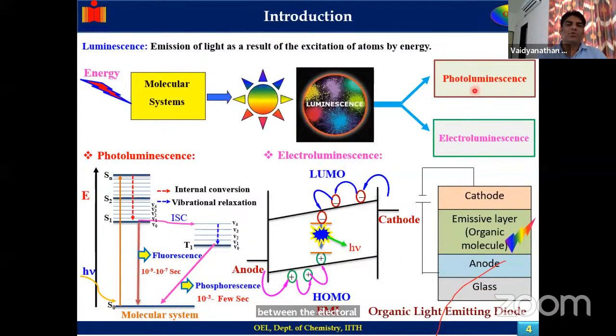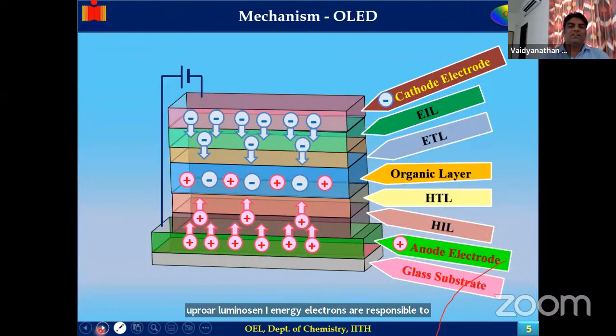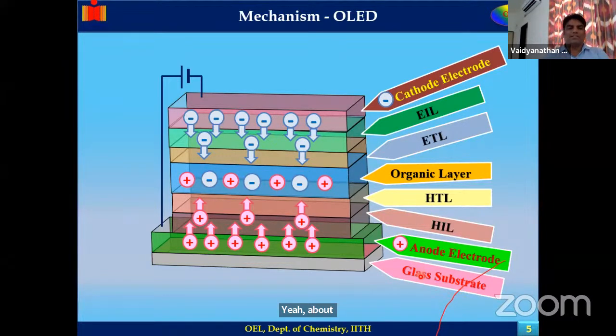Here in photoluminescence, the photon is the responsible source to get a luminescence, whereas in electroluminescence, high energy electrons are responsible to get electroluminescence. So you can see that in order to get emission from the OLED device, you need to have multiple electrodes and layers. One is the cathode, electron injection layer, electron transport layer, organic layer, that is the emissive layer. Then you have a hole transporting layer, a hole injection layer, the anode, and then the glass substrate.